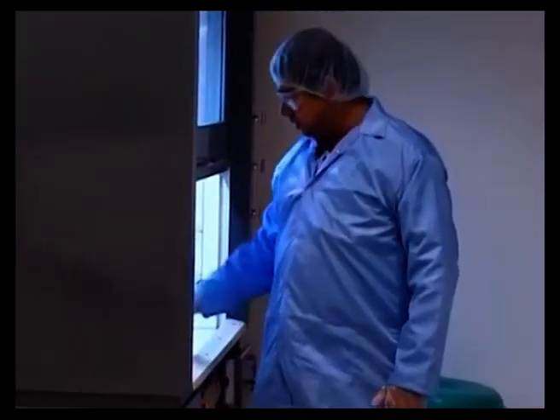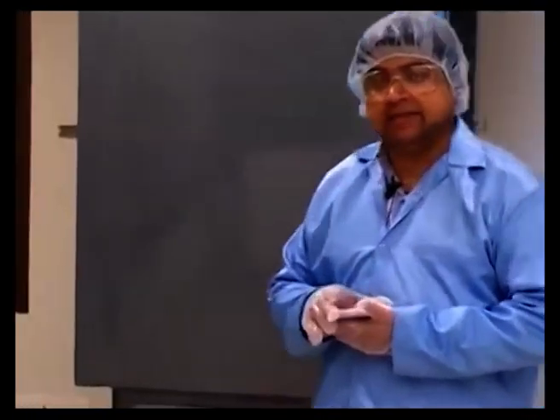So basically what we do now is to take this wafer that we just made super clean using Piranha process and take it to an oven. The oven basically that we are using here is a gravity fed convection oven, which actually is based on the principle of free convection. There are a set of heater coils at the bottom, and there is a current of air, heated air, which actually makes the temperature uniform. There is a PID based controller using thermocouple, which is somewhere at the floor of this particular heater.